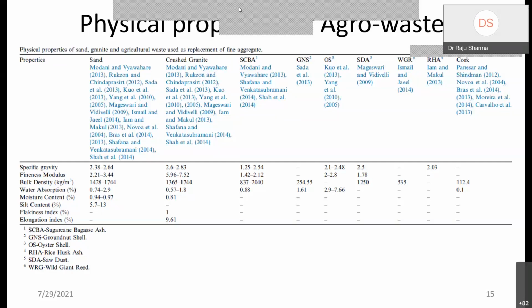You can see the oyster shell also has 2.1 to 2.48, so it is a good kind of replacement as a filler with the sand. You can see the specific gravity right here, so it can be replaced, it can be used, but it cannot be used solely for producing lightweight aggregate unless you are choosing lightweight coarse aggregates, right? By only replacing the sand with the OS, you cannot produce lightweight concrete. But maybe only by replacing the sand with the SCBA, right, you can produce lightweight concrete, right?